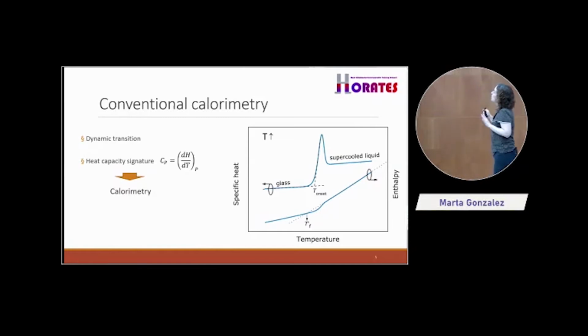Okay? So I'm showing you also these curves because at the end of the talk or in the middle, I'm going to show you a lot of calorimetry curves. So it's important that you identify what this means. This is the specific heat or the heat capacity, depending on if you normalize by the mass of the glass. This is of the liquid, okay? We have here a transition, this transition from glass to liquid. And here we have this excess enthalpy that we had because we were heating too fast, okay? So in this way, you understand the curves.